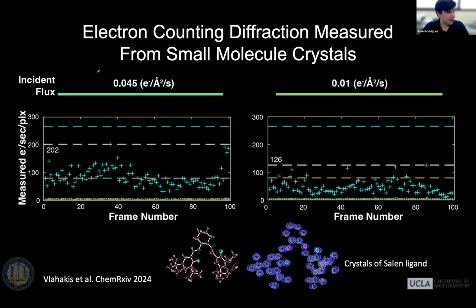what we might find is the best condition for diffracting from these kinds of molecules and these kinds of crystals. And so we chose to sample everywhere between 0.1 electrons per angstrom squared to 0.01 electrons per angstrom squared in incident flux, and then mapped as a function of given tilt series how many electrons were observed per given pixel. We mapped those distributions, and we also charted what the maximum counts were for any given frame. And you can see that those maximum counts sometimes exceed the 100 electrons or 200 electrons per pixel mark, indicating